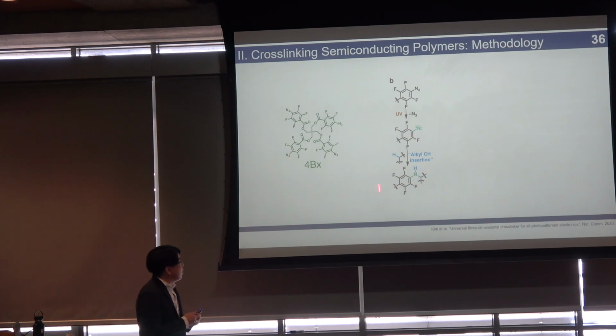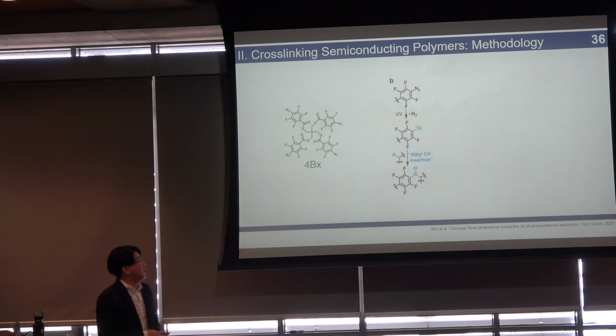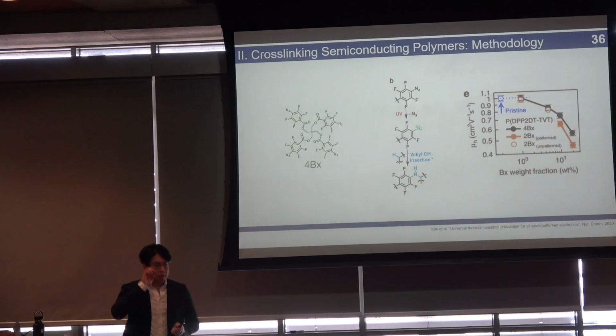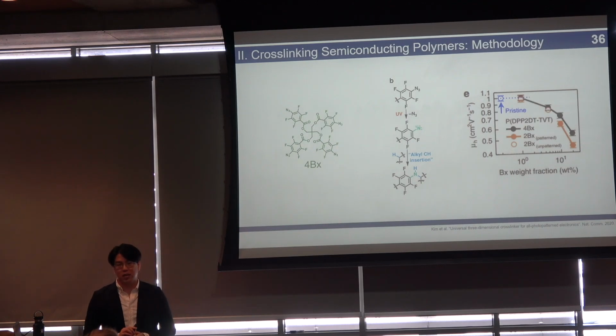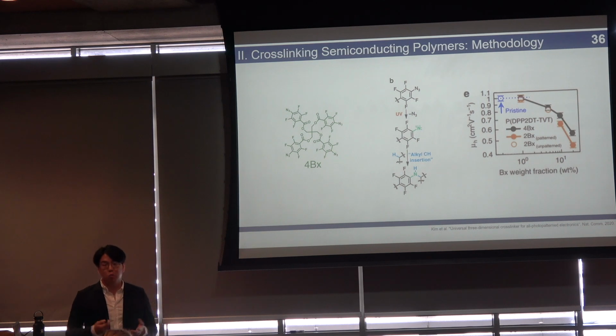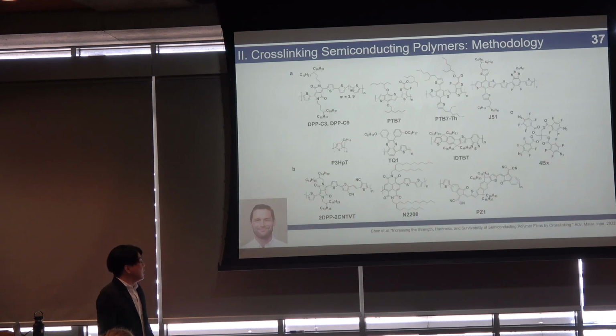And they undergo a process called CH insertion when exposed to UV light. And the authors of this paper showed that if you make transistors that are cross-linked, you could actually add about 1 weight % without impacting the hole mobility of your polymer films. So that's what we did.